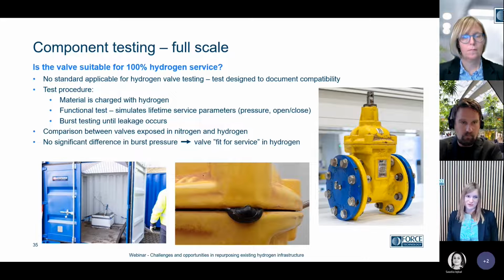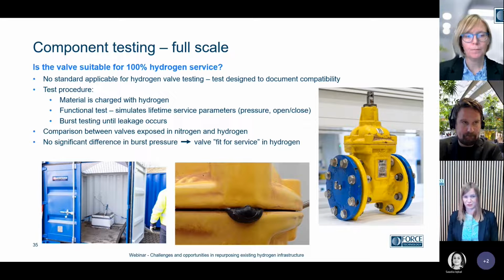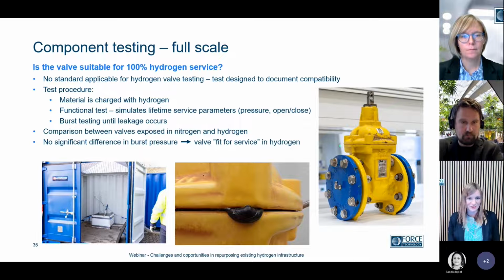And a comparison was made between valves exposed to nitrogen and hydrogen to see if there was a reduction factor in the burst pressure. We did not see a significant difference in the burst pressure. In fact, both burst pressures for hydrogen and nitrogen were a factor 10 of the design pressure. Hence, we did not see any embrittlement effect. As we can see in this center image, the weak link was the gaskets. And that's another area for investigation.